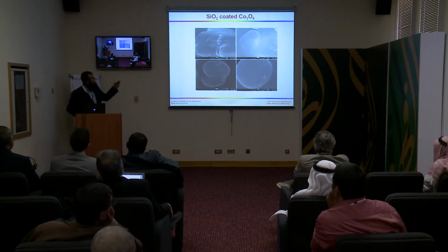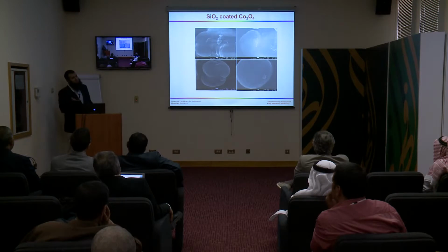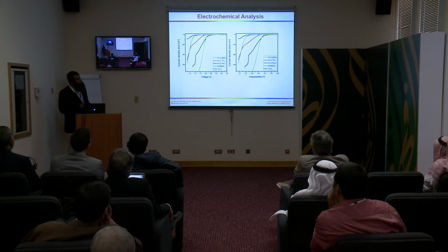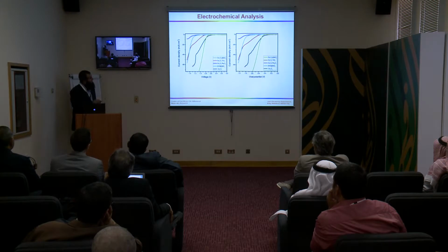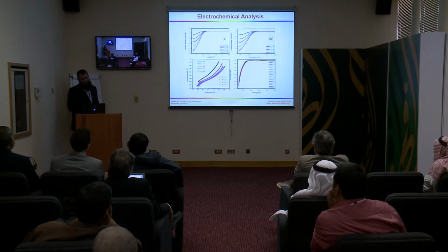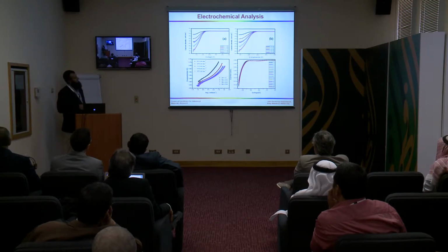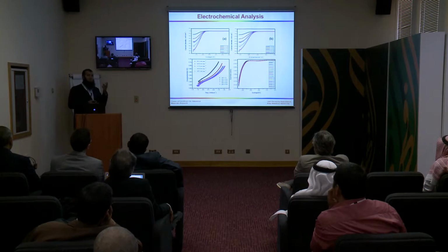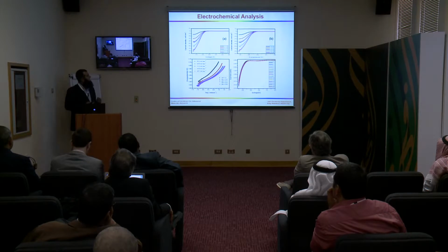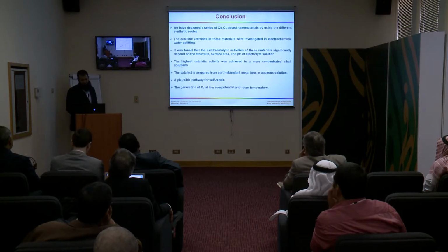So we decided to compare the result with the previously used hard silica template. When we studied the electrochemical property, we compared this material with other materials like cobalt oxide, cobalt-doped tin oxide, and iron. But this silica-templated material showed high current at low overpotential. In a similar way, we studied the pH effect as well as the stability. So this means that maybe the porous material helps in the transport of the charge carriers, and that's why it shows high current density.